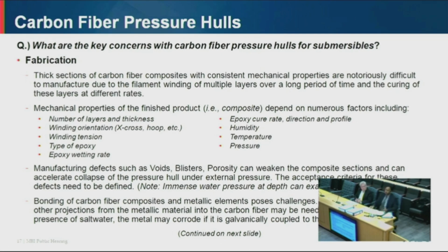Then the type of epoxy resin that is used for creating the composite has an impact on the strength of the pressure hull. So aerospace grade epoxies may not be suitable for high pressure underwater applications, okay? So then there are other factors such as the epoxy wetting rate. That means how much epoxy can you coat on the carbon fiber strands. Then the epoxy curing rate. If you don't follow the correct curing profile, your mechanical strength may differ.